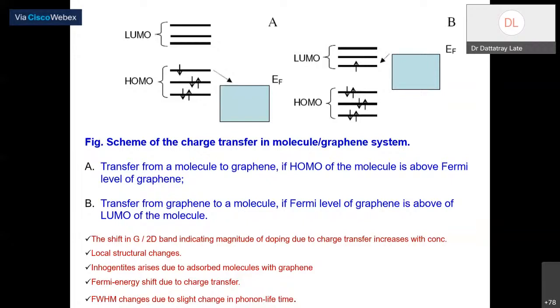what happened at the molecular level? Transfer from molecule to graphene, when the HOMO of the molecule is above the Fermi level of graphene, and in another way, maybe transfer from graphene to molecule, when the Fermi level of graphene is above the LUMO of the molecule. Basically, there is a change in the G band and 2D band. I just mentioned local structural change, Fermi level change, like the opening of the band gap, and many things happen.